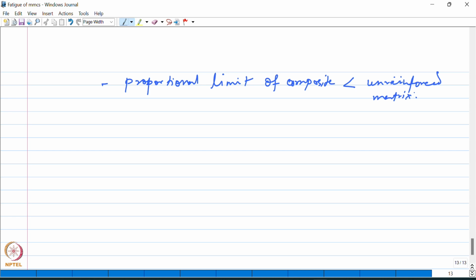However, you can see an impact of this lower proportional limit in the sense that, at least theoretically, at low stress levels, the average plastic strain in the composite may be greater than what is experienced by the unreinforced material at the same stress. Okay, so this is an impact of the lower proportional limit that you can see over here on the fatigue property of the material.